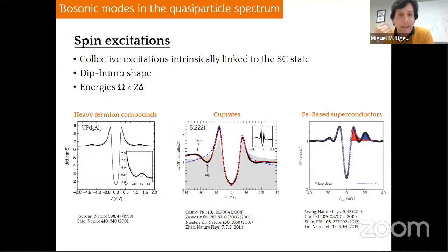A more promising candidate would be the existence of spin excitations, which are observed in many different unconventional superconductors. These are collective excitations intrinsically linked to the superconducting state. So they are present whenever the material is superconducting, and they should disappear when the material is not superconducting, so when it becomes metallic. The usual shape that they show is similar to what we see. It's a dip-hump shape, as you see here, for these heavy fermion compounds, for this cuprate, and for these iron-based materials. And the energies at which they show up are also quite similar to those we observe below 2 delta.